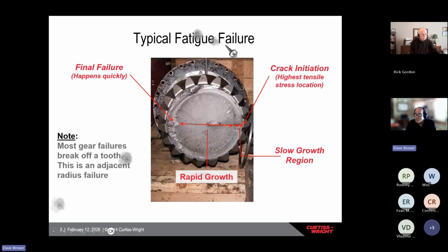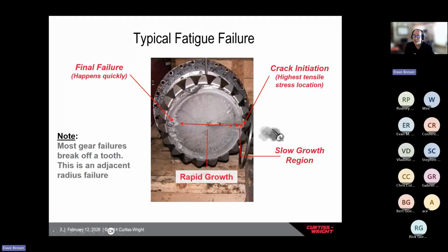So this is a pretty good sized shaft here, and this is a pretty nice looking fatigue surface for teaching a class. What happens is that metal fatigue starts slowly. So the fatigue crack did start here at the 3 o'clock position. Let's say it took 250,000 cycles for the fatigue crack to start.